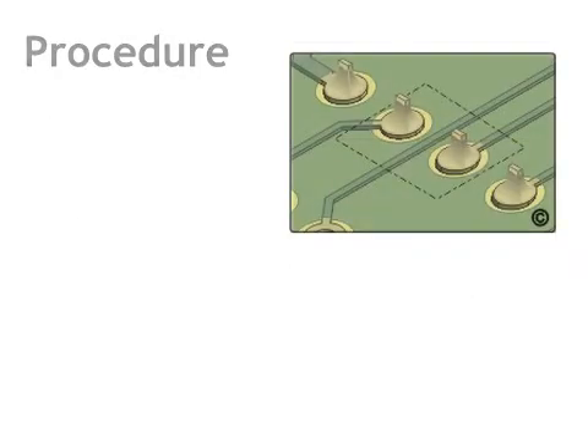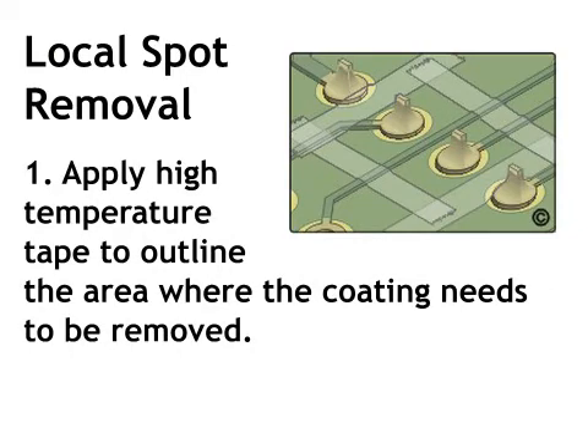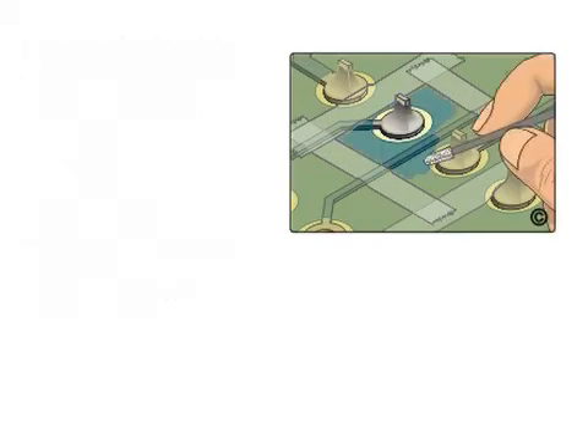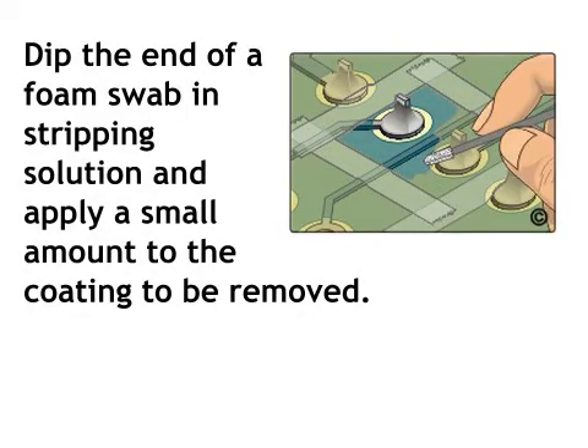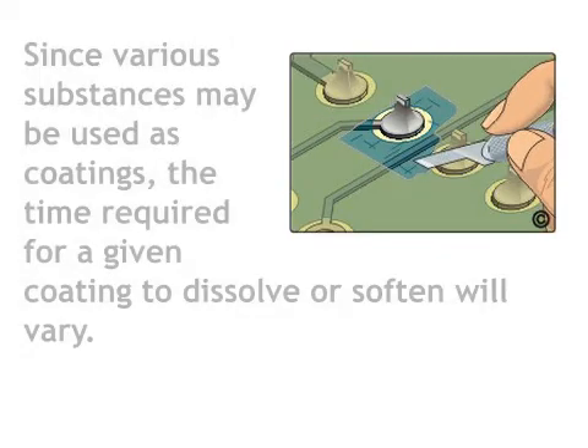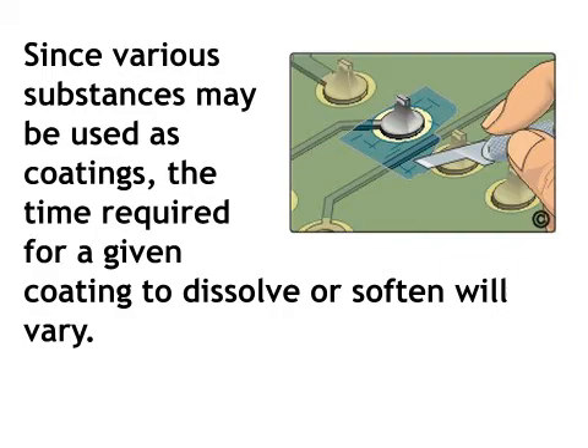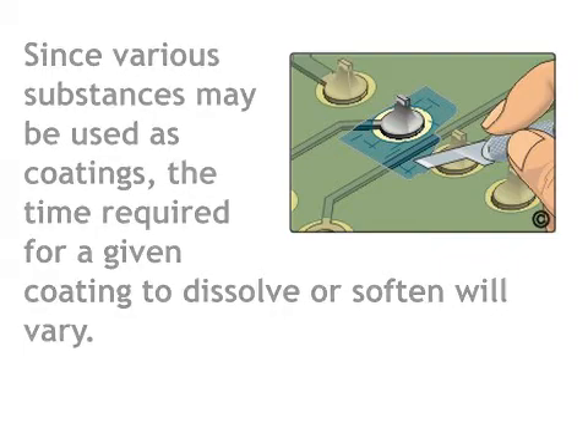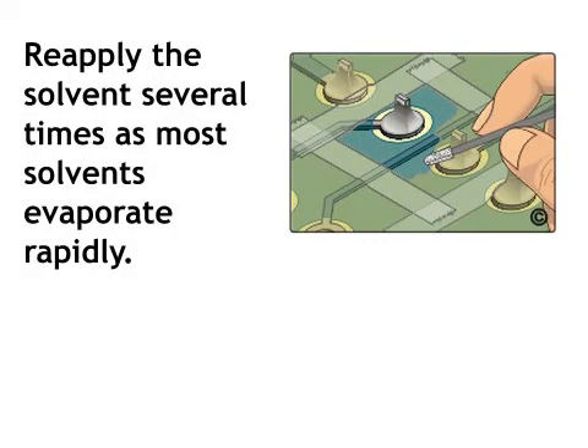The procedure follows. Local spot removal. Step 1. Apply high temperature tape to outline the area where the coating needs to be removed. Dip the end of a foam swab in stripping solution and apply a small amount to the coating to be removed. Since various substances may be used as coatings, the time required for a given coating to dissolve or soften will vary. Reapply the solvent several times as most solvents evaporate rapidly.